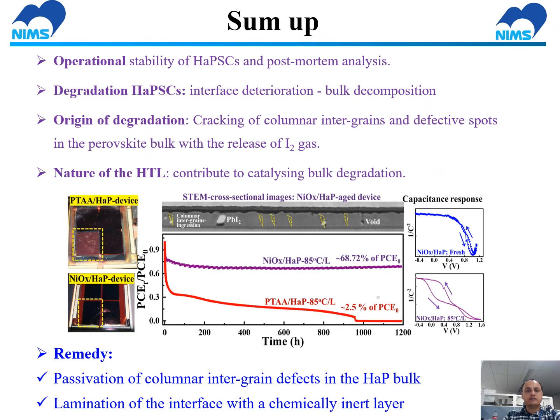To sum up, we analyzed the operational stability of perovskite solar cell under thermal stress and performed the post-mortem analysis. We found the degradation of perovskite solar cell is caused by interfacial deterioration and bulk decomposition, and it is led by the cracking of columnar intergrain and defective spots in the perovskite bulk with the release of iodine gas, and the degradation is also affected by the nature of the HTL layer. To have a remedy for degradation of perovskite solar cell, we have to passivate the columnar intergrain defects in the perovskite bulk. Also, we have to laminate the interface with a chemically inert layer.